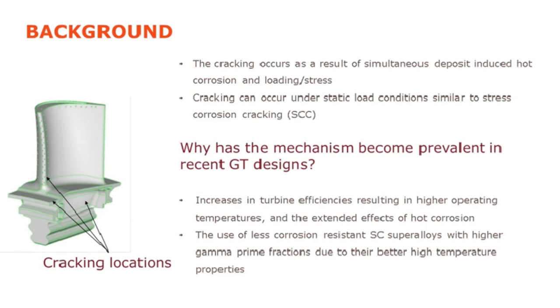The second reason is sort of related. Because, again, we want to achieve higher temperatures to improve efficiencies, we're looking at using materials which have higher gamma prime fractions in order to achieve better high temperature properties, so better creep properties and things like that. But by increasing the gamma prime fraction, we actually reduce the refractory element concentration or weight percentage, and those refractory elements are really very good for building up protective oxides. So with a lot of the really good high temperature superalloys, they're a bit worse, particularly at lower temperature corrosion. So there's a bit of a trade-off there, and that's another reason I think we're seeing this mechanism become more of an issue as we use those high temperature, high gamma prime fraction superalloys.